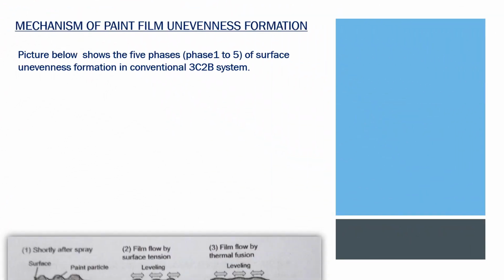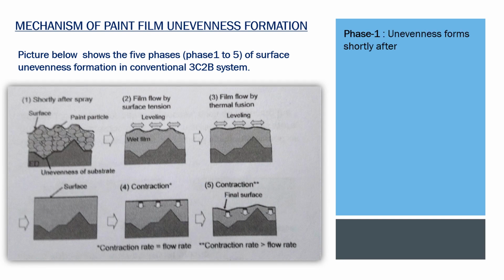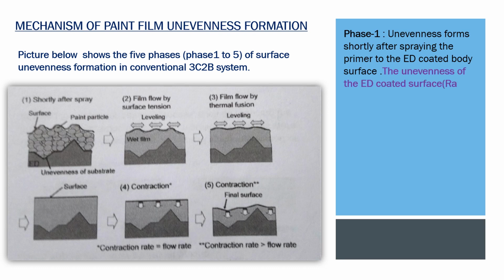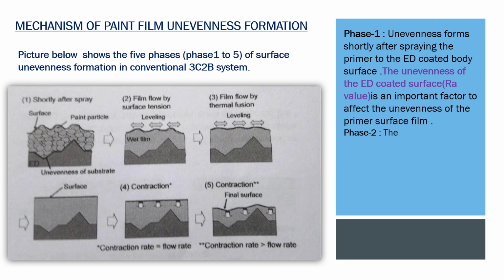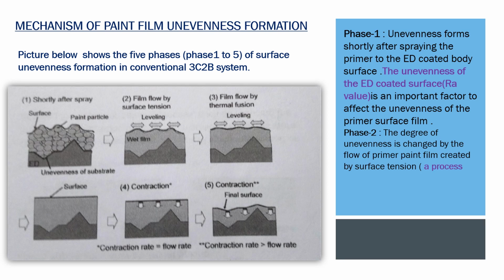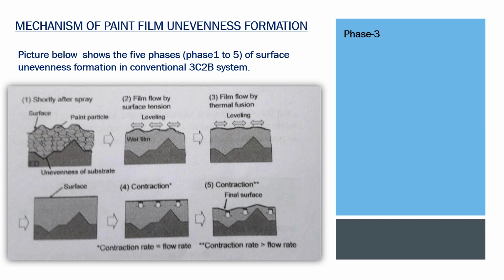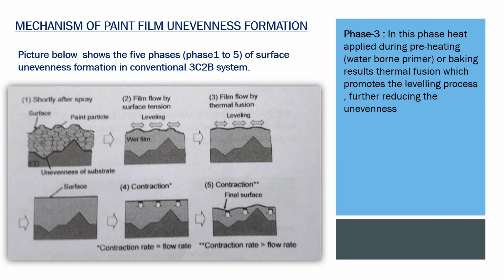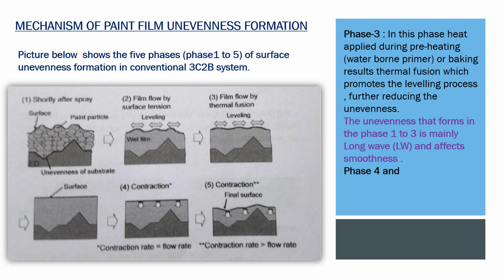Mechanism of paint film unevenness formation. Phase 1: unevenness forms shortly after spraying the primer to the ED-coated body surface. The unevenness of the ED-coated surface, the Ra value, is an important factor affecting the unevenness of the primer surface film. Phase 2: the degree of unevenness is changed by the flow of the primer paint film created by surface tension, a process called leveling. The degree of leveling increases as the viscosity of the flowing primer decreases. Phase 3: heat applied during preheating of the water-borne primer, or baking, results in thermal fusion, which promotes the leveling process, further reducing the unevenness. The unevenness that forms in Phases 1 to 3 is mainly long wave, LW, and affects smoothness.